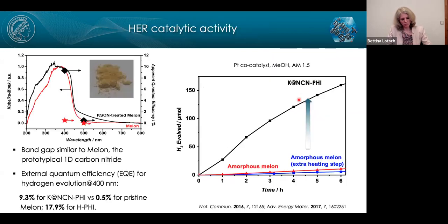So, first of all, what we did is we compared this PHI type carbon nitride with the classical melon type carbon nitrides. And as you see here, the band gap is essentially the same, 2.7 eV. But when you look at the hydrogen evolution activity of this PHI, then you see that it vastly outperforms melon-type carbon nitrides by about a factor of 20 or so. So we are achieving quantum efficiencies, let's say, around 15 to 20%. So that's quite substantial. And we were wondering actually, where does this difference come from?